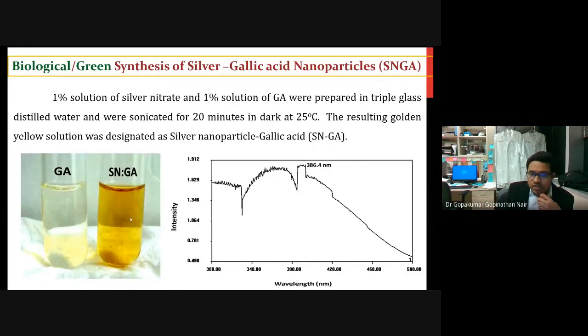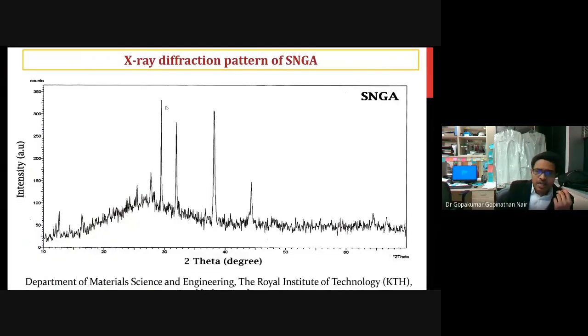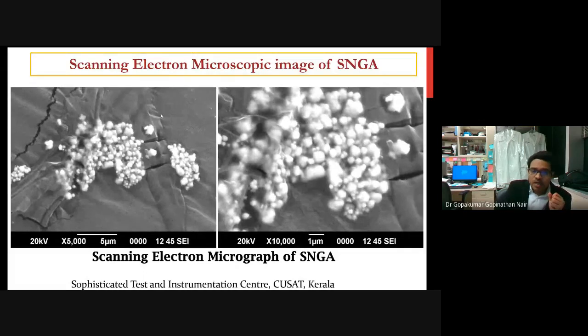And when the nanoparticles are formed, it will give a golden brown solution, and it is called silver nanoparticle gallic acid complex. And I have done a UV scanning, in the range of 250 to 400, which shows the formation of nanoparticles. And I have also done the XRD imaging of the nanoparticle formation, and it has shown a good nanoparticle complex of the drug. And I have also done scanning electron microscopy of this, and found that the nanoparticles were in the nanometer size range, and it was done at the sophisticated facility, STIC, CUSAT, Kerala.